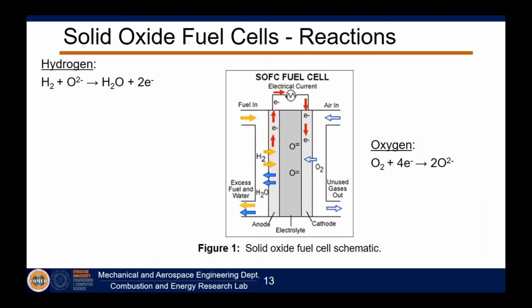On the cathode side, we typically supply air. You can supply complete 100% oxygen, but it's obviously much more expensive to do that. So we usually try and supply air. The air comes in. The oxygen will actually diffuse, just regular diffusion, through this porous cathode layer. It comes to what's called the triple phase boundary, where the electrode meets the electrolyte.